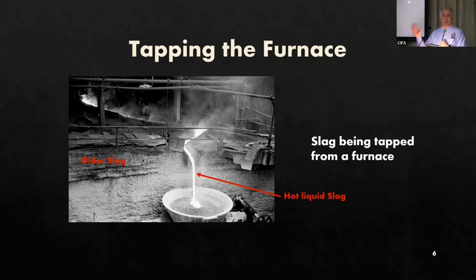You can see in this picture hot liquid slag flowing out of a furnace and then collecting in a rail car that was designed to transport that slag away from the furnace. You can also see in the background there those horizontal layers. That is also slag that was previously tapped from the furnace, has become like rock and is sitting there behind the ladle that's picking up the slag.